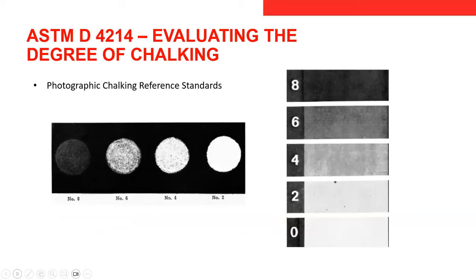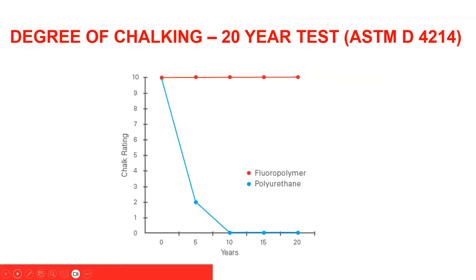And even though we're just talking about aesthetics in this presentation, you start losing the film, the top coat, and it's going to start attacking those underlying layers. In the case of a 3-coat system, those underlying layers, the primer and the intermediate coat, are really designed to protect the structure itself from weathering and corrosion. And so you're starting to lose the overall protective layers, as well as obviously the aesthetic portion of that coating system.